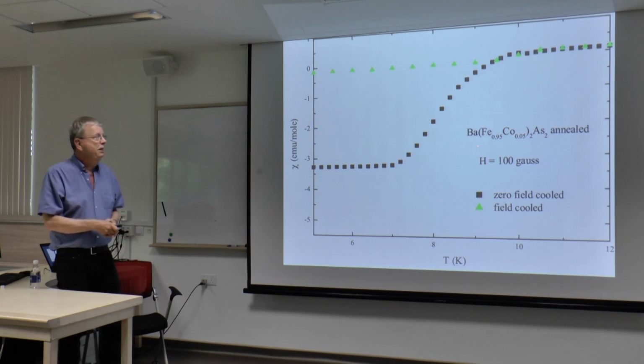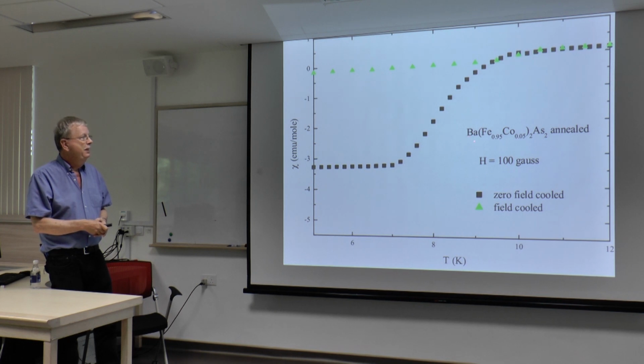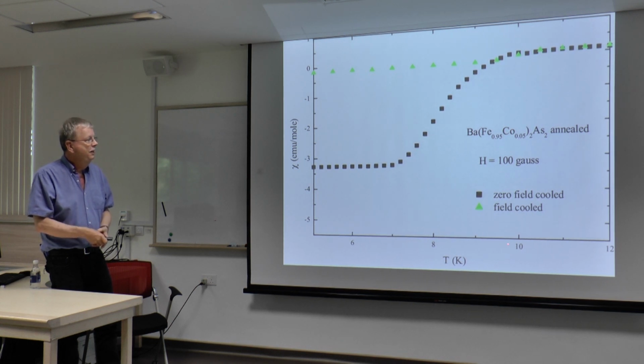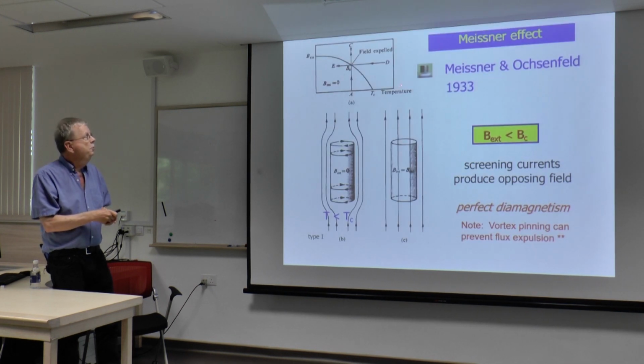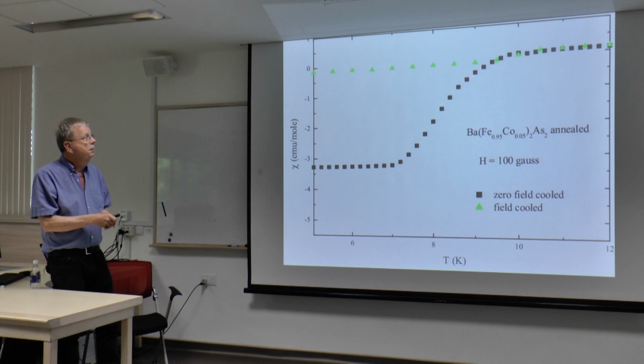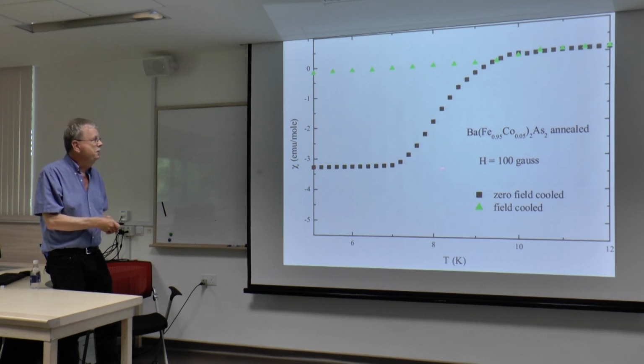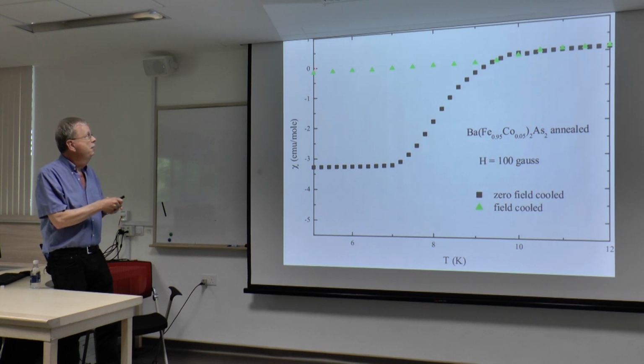So this is just some data out of a file that I carry around with me. This is an iron-based superconductor. This is not quite the best stoichiometry for TC, but here's a transition temperature, and if you cool it in zero field, which would be along this line, then you get down to here, then you turn a small magnetic field on and measure the susceptibility, and it looks rather diamagnetic. In other words, a -1/4 pi would be perfect diamagnetism. So on this scale it might be a little further down here. But anyway, you get what's called shielding, and it looks pretty diamagnetic, pretty superconducting.